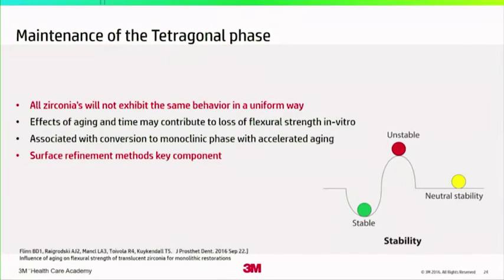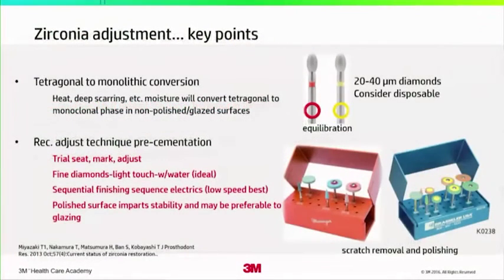So if you ask me what this really means, it goes back again to using a quality zirconia. We do know that the effects of aging over time can contribute, as we saw earlier, to a degradation in the flexural strength, at least in vitro, for the material. This is associated with the conversion of the material back to the monoclinic phase, too much of which can produce a problem for the material and potentially contribute to early failure. To understand this, surface refinement methods are a key component.